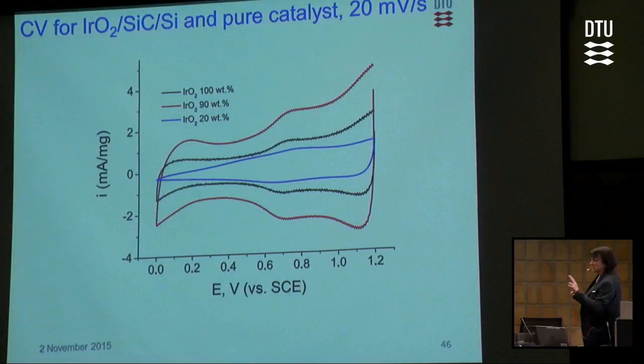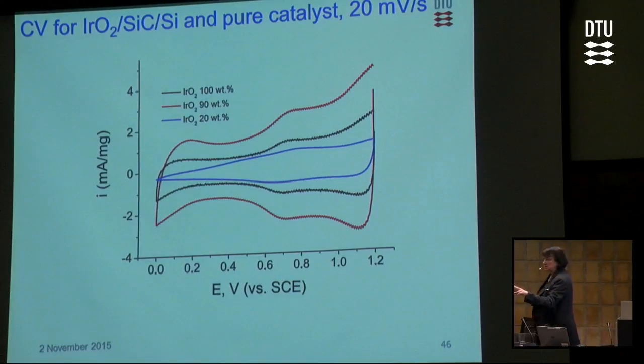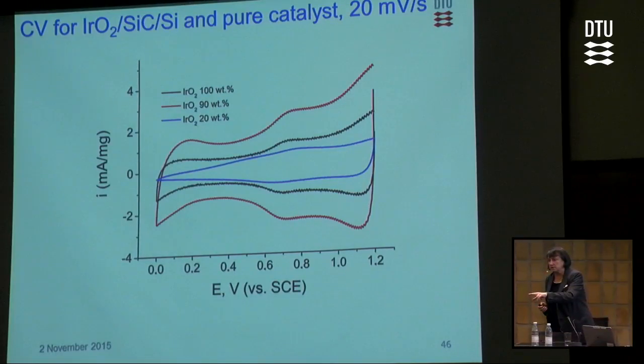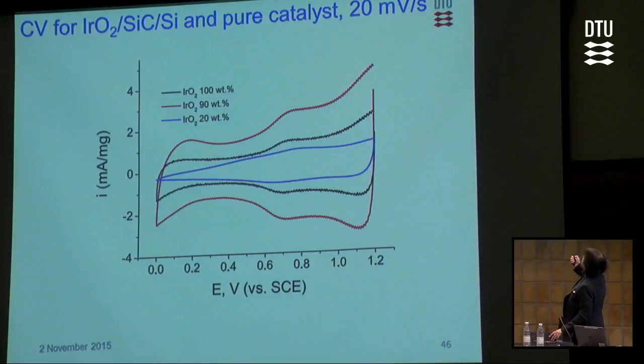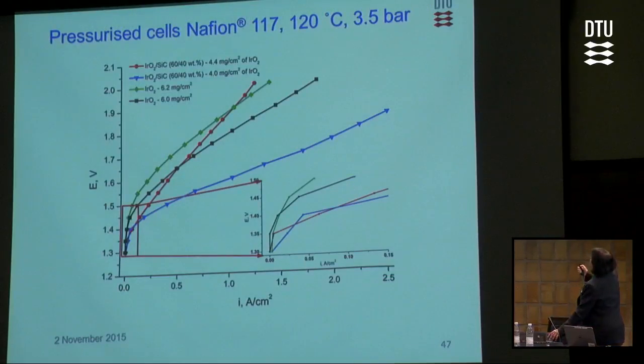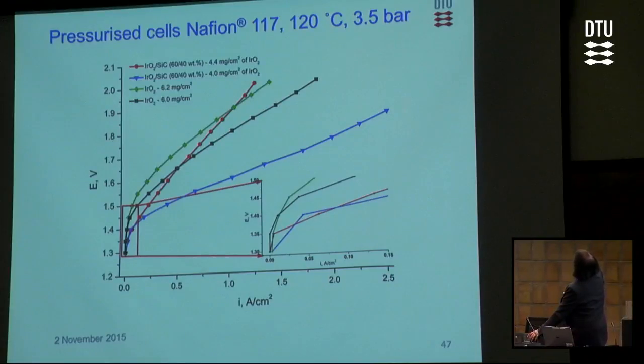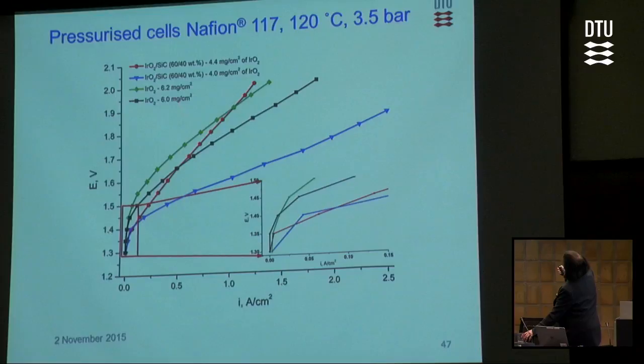But we did two nice things. First, we diluted the iridium dioxide a little bit with a silicon carbide support. At least at 90%, it was better than pure iridium. At 3 bar, it was fantastic. That was on silicon carbide, and this was on pure iridium.